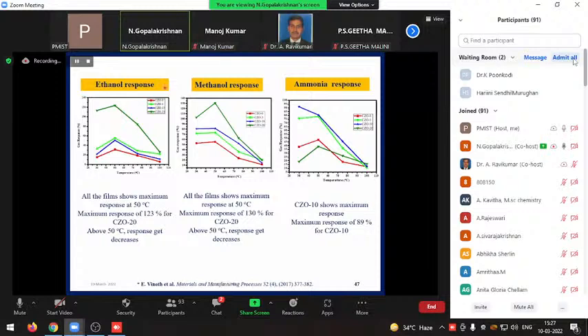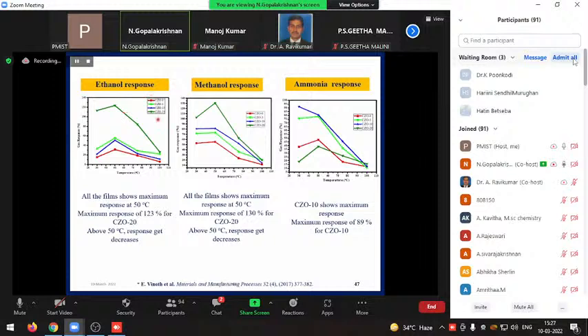What I want to tell is that the red one is pure zinc oxide, and the other colors are the different dopant concentrations. So upon doping with cadmium, we enhance the gas sensing ability. For a particular temperature or particular dopant concentration, we get the maximum sensor response. In summary, the gas sensing efficiency is enhanced upon doping with cadmium.